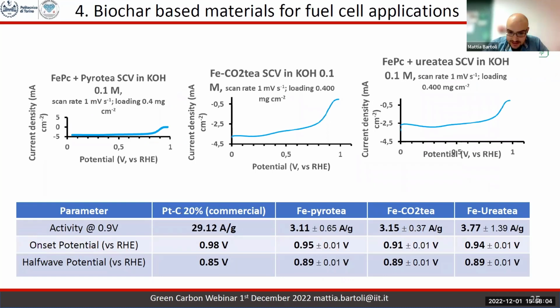What we saw is that even if we were far from the commercial one because we didn't match the activity, the onset potential and the half-wave potential were practically the same as platinum-rich catalysts. And if you compare the activity normalized on the surface area, our materials were considerably high. Consider that with the surface area up to 250, you obtain an activity up to 29 amperes per gram. We obtain 3 amperes per gram with a surface area that is 5 times lower. So something that you should keep in mind.